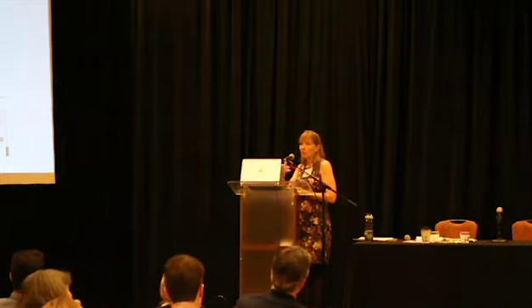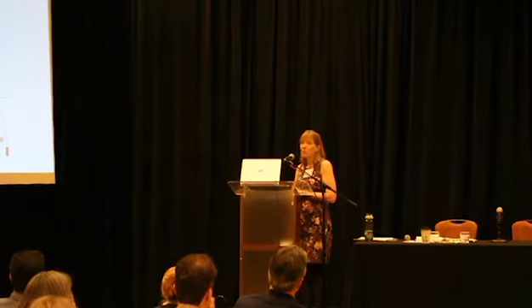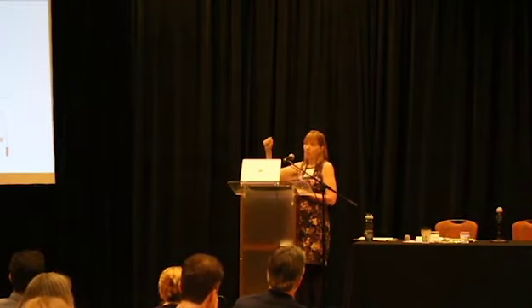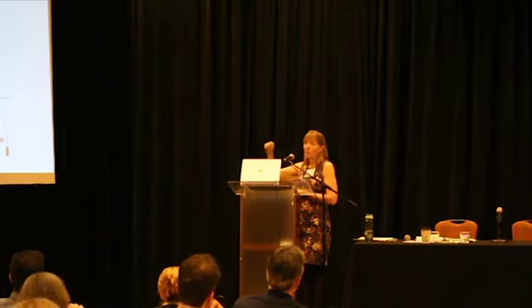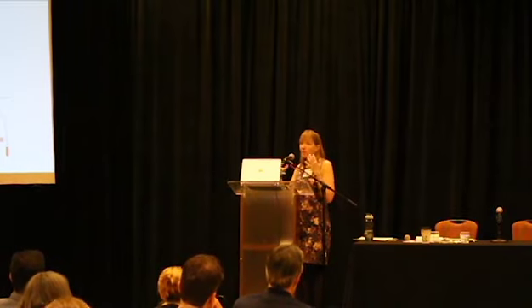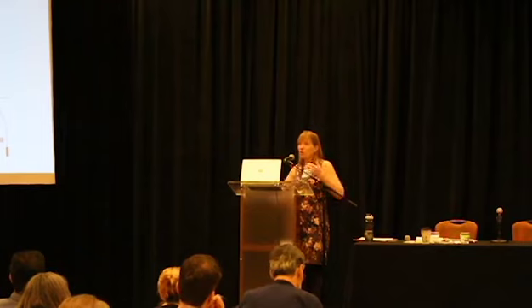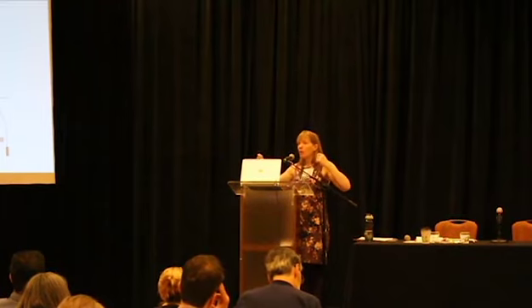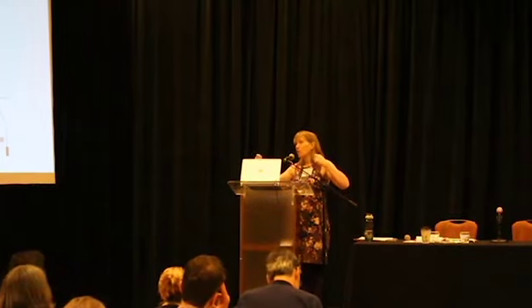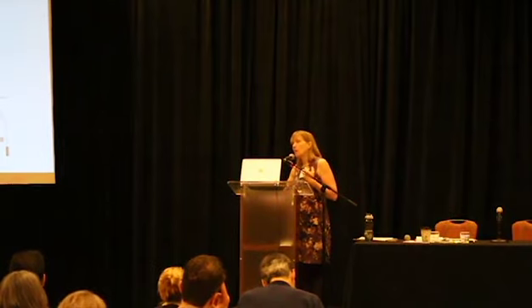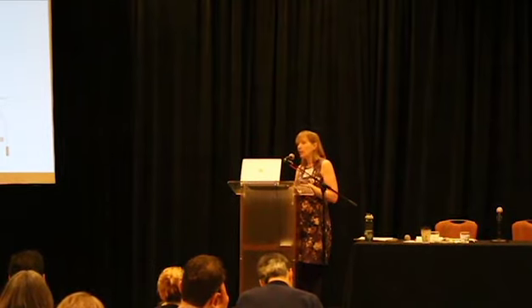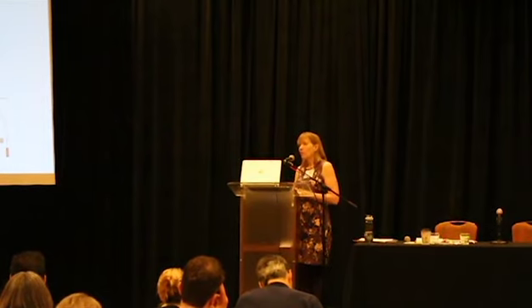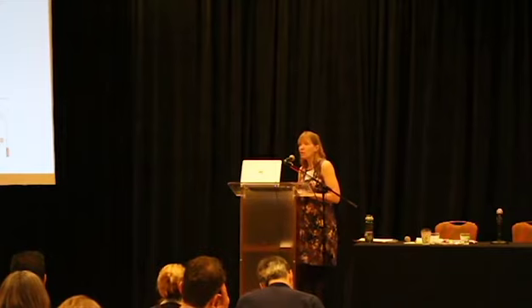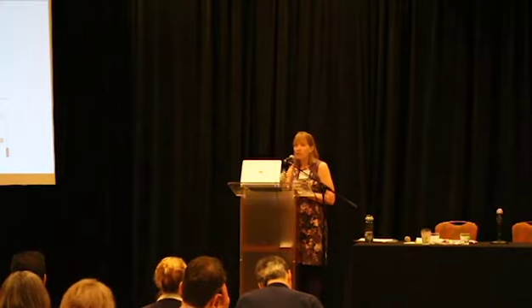one thing I forgot to mention is on those impressed current systems, if you ever see positive numbers at an impressed current system, have them shut it off. I said the first amount of cathodic protection does the most good, so always leave it on. But if they go out there and those numbers are reversed, what that means is that tank is being used as an anode, and it could cause that tank to fail very quickly. So if they have positive numbers, have them shut it off. The one and only time we shut off a system when we were out doing a class was we found the leads reversed.